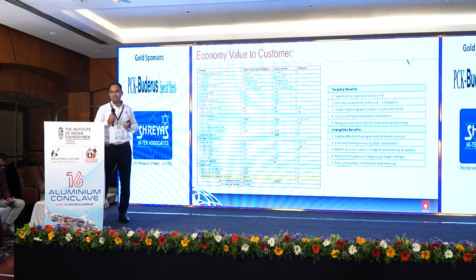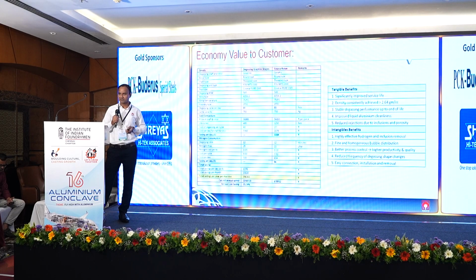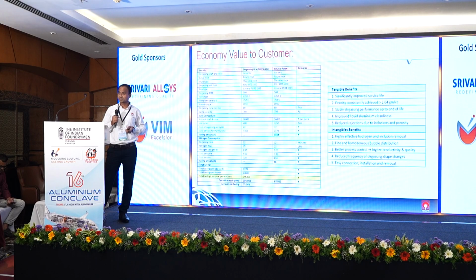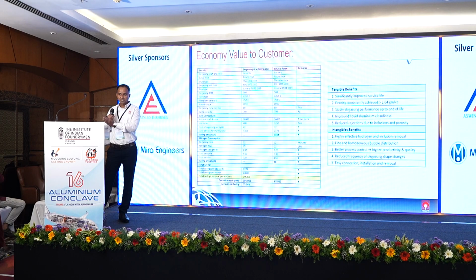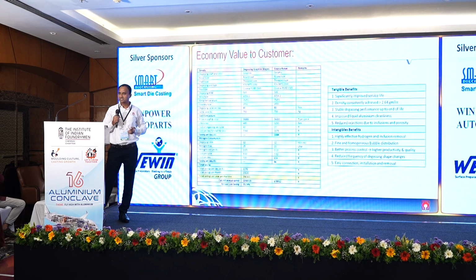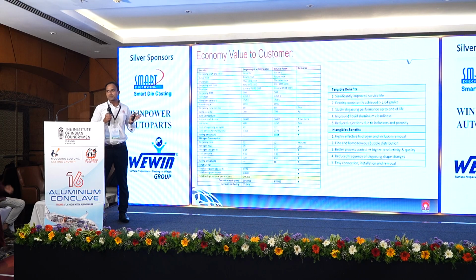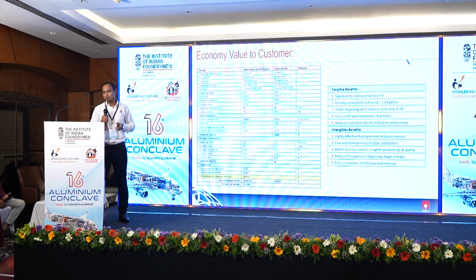Another big benefit is that whenever we change the graphite shafts and rotors, the DI is low for the first 3-4 cycles because of moisture pickup. The density index of those 3-4 cycles comes low, and we change graphite 3 to 4 times more often than Roton. So there is a chance of producing pinhole rejections. In the case of Roton, there is no chance of pin porosity rejection, because the changeover comes after 1500 cycles, whereas for graphite it is 400 cycles. So we can avoid these pin porosity rejections with the use of Roton.